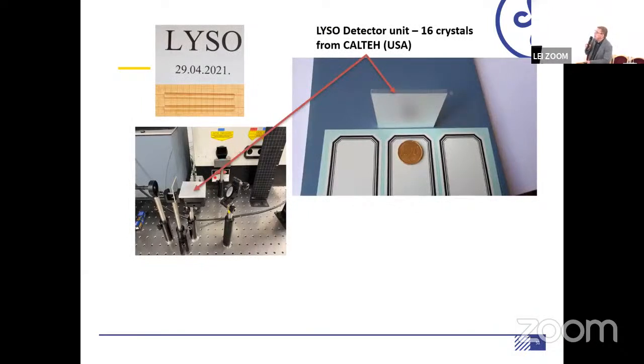This is just a detector unit produced from such a single crystal. You can see the detector which we obtained from Caltech, the California Institute of Technology, for our test in India, because we need to understand not only the radiation emission of such a detector, but also, since this is quite a big crystal, the uniformity of these crystals is very important. Even if there is some difference in signal of about 2%, this could be documented and used for further data correction.